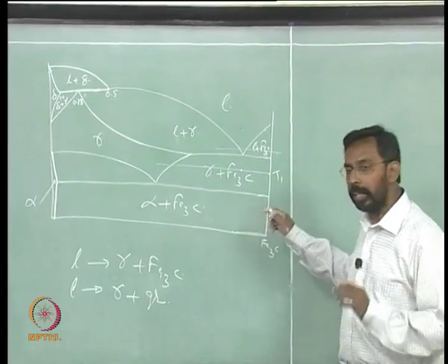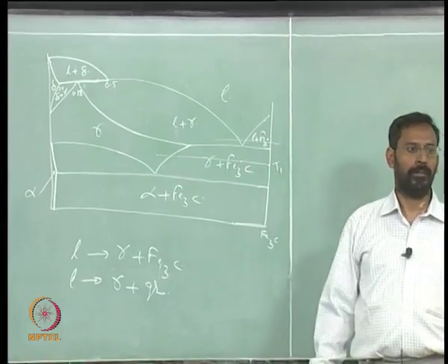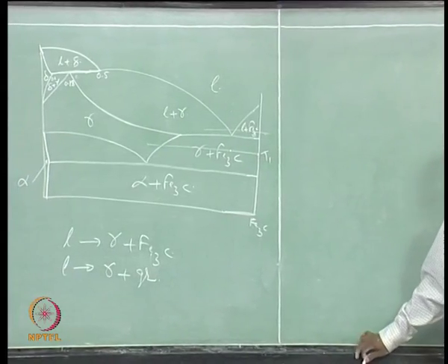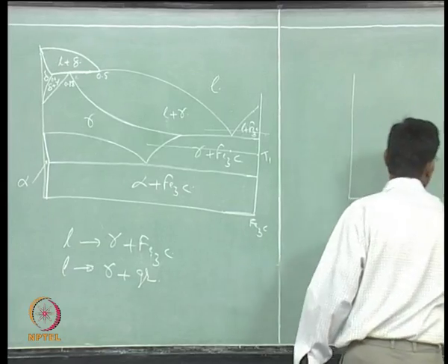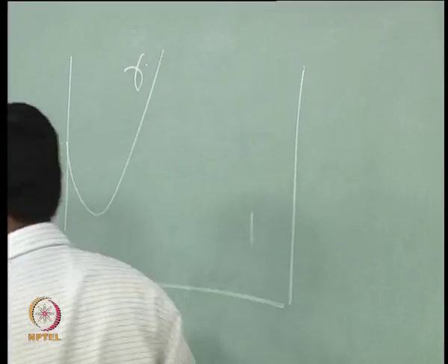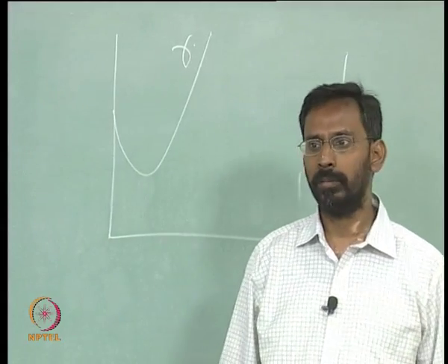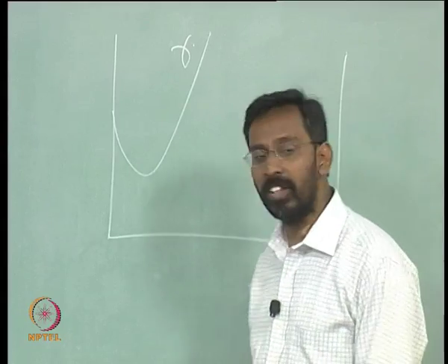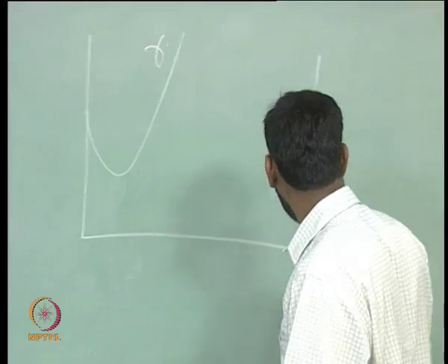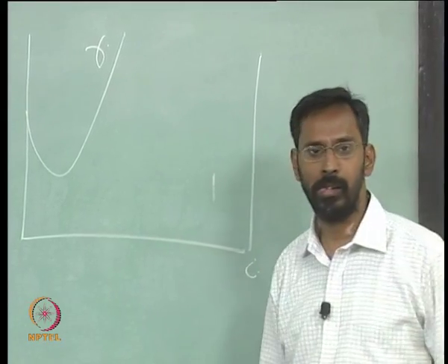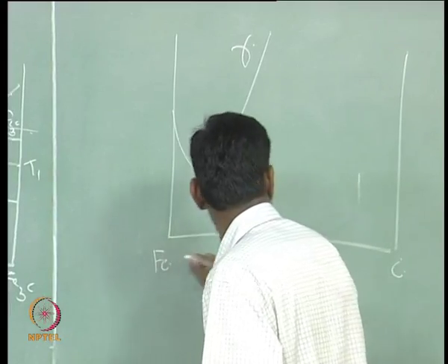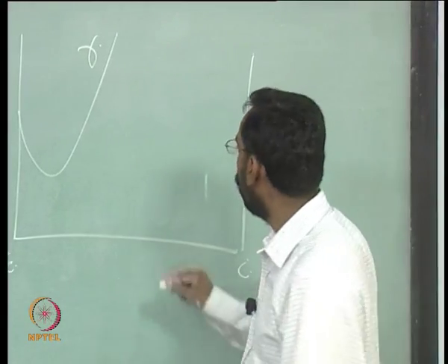Now let us look at the equilibrium between gamma, Fe3C and graphite, and if I look at that, what I see is that I have 3 phases. So, I should be able to draw a free energy curve with the 3 phases. If I draw that, one is gamma, this is gamma. Now, what about Fe3C? Fe3C is an intermetallic compound, a line compound with 6.7% carbon. And the other end I will put as pure carbon, that is my graphite. This is pure iron, this is pure carbon, 100% carbon, that means graphite, whereas Fe3C is